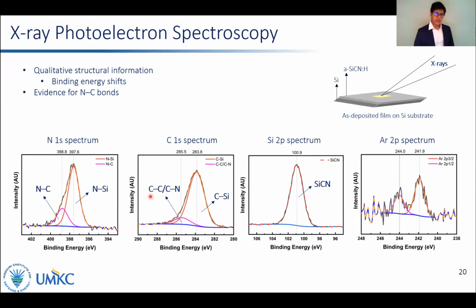In a similar way, the carbon 1s spectrum was also fitted with 2 peaks: one corresponding to carbon bonded to silicon, the other corresponding to both C-C or C-N bonds. The silicon 2p spectrum was fitted with 1 peak, ascribed to silicon in a mixed bonding environment.